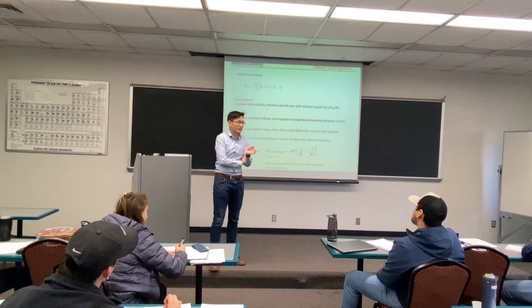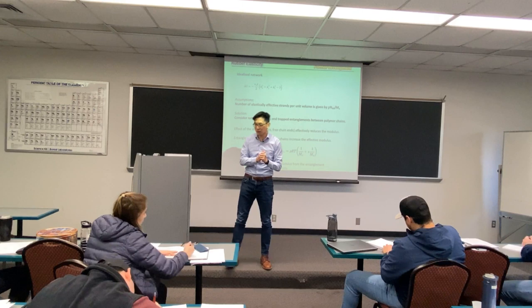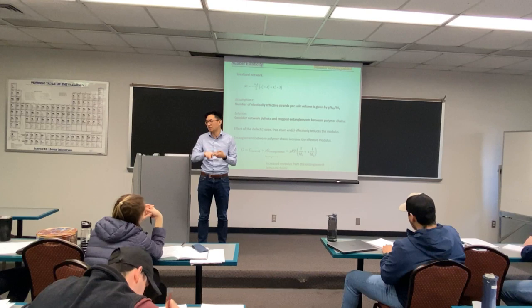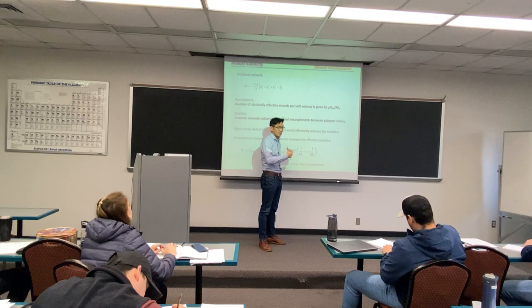I want to use, again, the example we talked about in the textbook. If X is equal to 0.5, let's use an example, polystyrene. Although it may not be a perfect fit there, Me for polystyrene is about 18K Dalton. That means above 18K, polystyrene will entangle a lot in the melt state. Now you can see, if your Mx is 18K, at a similar level, then this would increase your modulus by 1/3, right? This is X equal to 0.5.